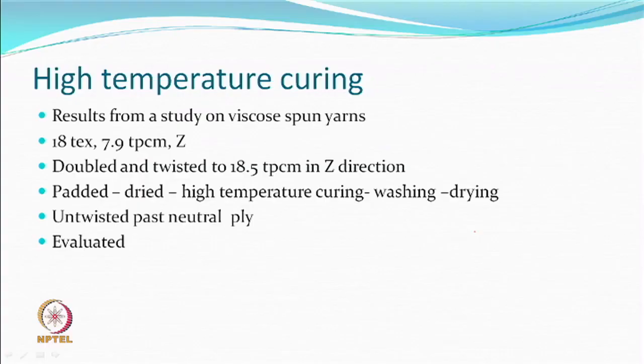So, cross-linking is a bulk change, property change in bulk. Like thermomechanical also change in the whole bulk. So, you can't have only surface being treated or treated more than the rest. So, people may not prefer flash curing as such, but you may go for high temperature curing. That means you dry initially at a low temperature and then cure at a high temperature, so that you can go faster. So, one example which I am just listing here is some of the viscose yarn, which was some